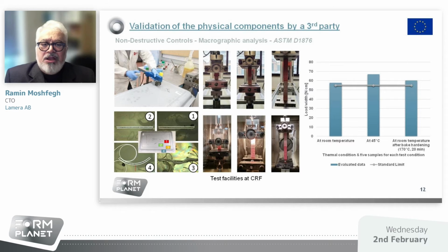So you can see that they made the non-destructive control, macrographic analysis, and the ASTM D1876. And it was very interesting for us that they made the experimental procedure in different temperature configurations, which somehow pretend that we are working with the forming process, and we are going from the painting process. So you can see that at room temperature, at 45 degrees, and bake hardening, simulated bake hardening. And you can see that the load per width values clearly fulfill the requirement CRF has, in order to say the material is okay, coming to our material department, and we can start to work with that one.